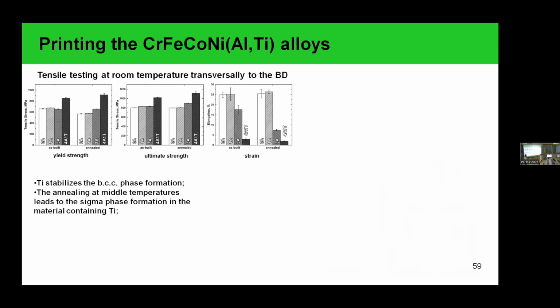So analyzing the tensile testing result of our material, it's presented only for room temperature. We see that in the as-built state, the materials of the four-component system and with aluminum demonstrate approximately the same strength characteristics. And only after heat treatment at 800 degrees Celsius for 30 minutes, we see the increase of the strength characteristics for the materials with the higher aluminum addition. But they also demonstrate a drop of ductility. The same material demonstrates a drop of ductility at the as-built state, and a further loss of ductility after annealing.